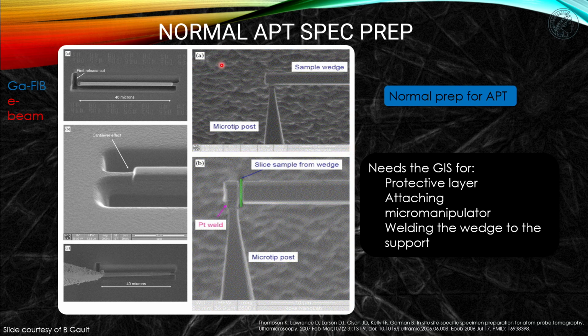So one of the major methods that this is done, and I'm now borrowing a lot of the slides that were kindly shared with me by Baptiste Gault, in this particular setup you can basically produce a long cantilever, and that cantilever can then be used to chop off the end of the cantilever and deposit it on a pre-prepared post.